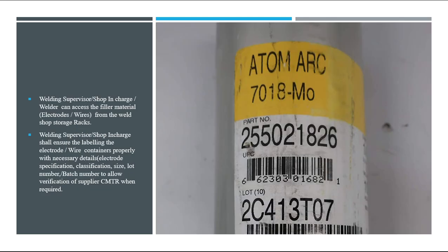Then the welding supervisor, shop in charge, and welder can access the filler material from the weld shop's storage rack. The welding supervisor and shop in charge shall ensure the electrode and wire containers are properly labeled with the necessary details like electrode specification, classification, lot number, batch number, and allow verification of the supplier's CMTR when used. Why are lot number and batch number important? Because sometimes when your welding fails and you test it to find the reason for the failure, the lot number is very essential. In tensile testing or hardness testing, if your batch fails, you can identify in how many components this batch of electrode was used. So you can track those components from your welding log sheet.